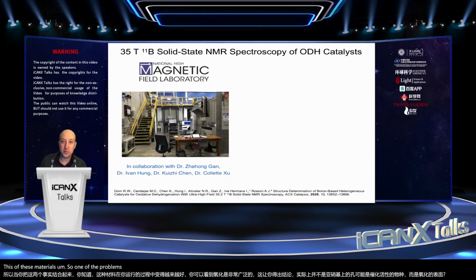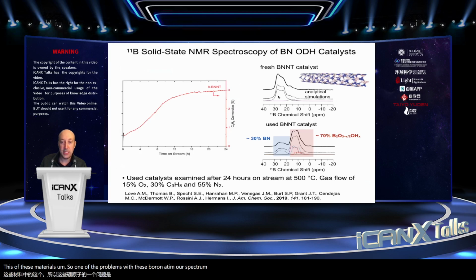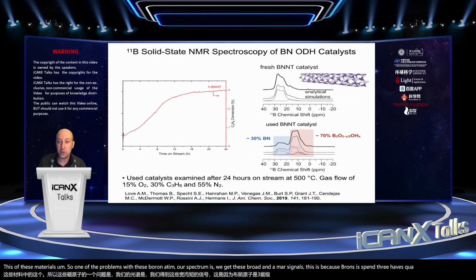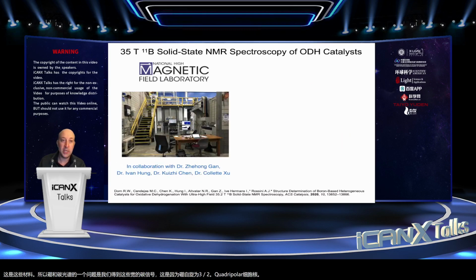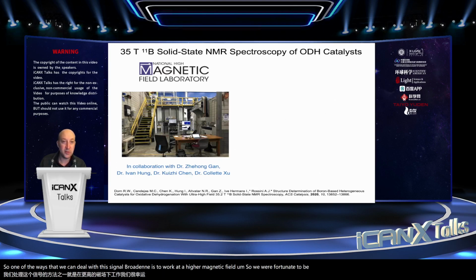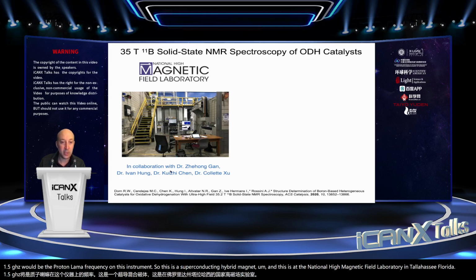So one of the problems with these boron NMR spectra is we get these broad NMR signals. This is because boron's a spin 3/2 quadrupolar nucleus. So one of the ways that we can deal with this signal broadening is to work at a higher magnetic field. So we were fortunate to be able to use this 35 Tesla, 1.5 gigahertz would be the proton Larmor frequency on this instrument. So this is a superconducting hybrid magnet. And this is at the National High Magnetic Field Laboratory in Tallahassee, Florida, working in collaboration with Dr. Zhehong Gan and Dr. Ivan Hung.